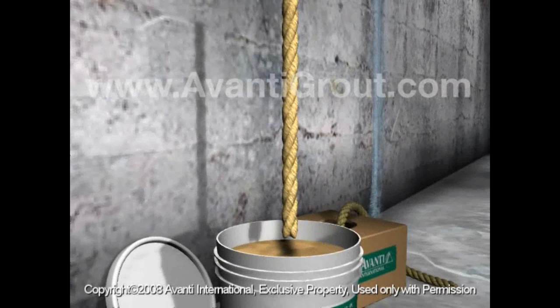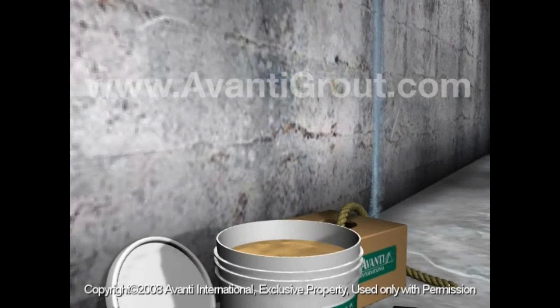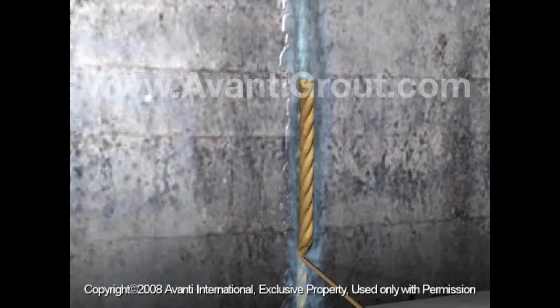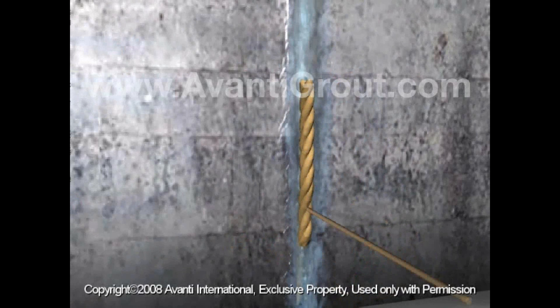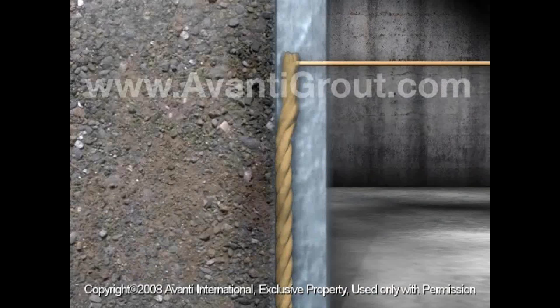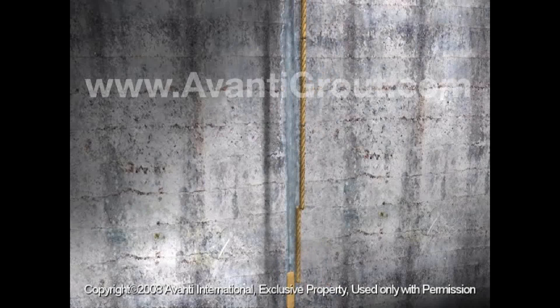In the Oakum Soakum animation, we see a wall that is leaking. You see the oakum rope and you see the grout pail. Typically, the grout is mixed into the oakum rope to keep the grout in place as you put the mixture into the leaking area. After you place it in the leaking area, the material will expand, adhere, and compress against the sides of the structure, stopping the leak.